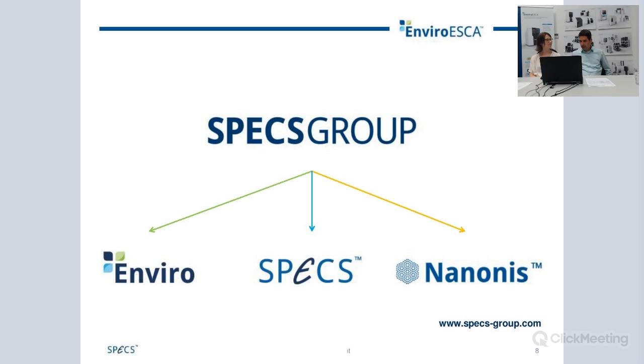And just to add for this charge compensation, we tried different gases and there was no big difference between, for instance, argon and nitrogen. But sometimes it showed that water vapor is working better than other gases, for example, with some samples, and then it's quite a severe effect in the full width half maximum of the spectra. And you can optimize, for instance, the carbon monoxide 1s spectrum using water vapor instead of argon or nitrogen.